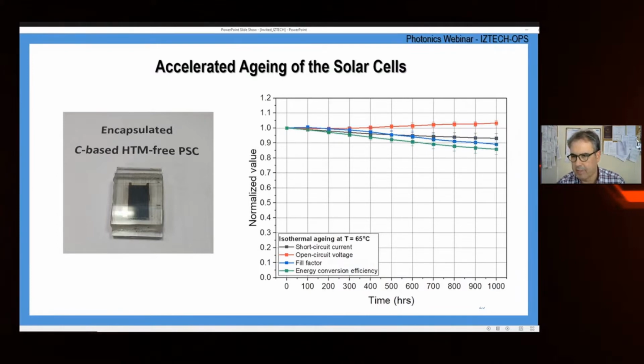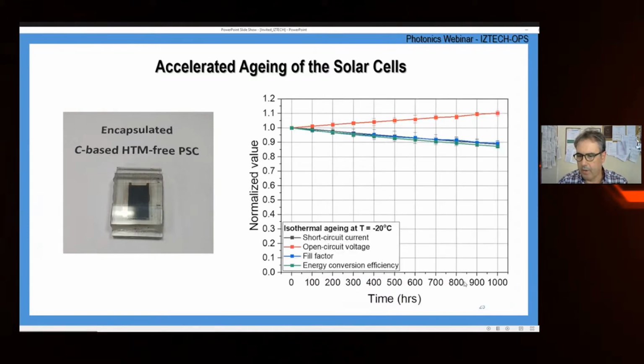isothermal aging at 65°C. We see some degradation, which is, as I said before, around 15%, basically coming from the short circuit current and fill factor. On the other hand, we have an increase in the open circuit voltage. And finally, we obtain a lower energy conversion efficiency after 1000 hours. Also, we have isothermal aging at -20°C. We have some similar behavior here with the voltage and small deviations from the initial performance, approximately 10%.